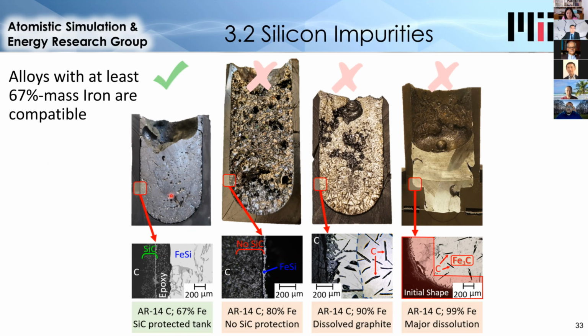So this first figure shows an iron silicon mixture that's 2/3 iron contained in a graphite infrastructure. Silicon carbide still formed at the interface, and an added benefit is that it actually shrinks slightly on freezing because iron shrinks and silicon expands, and the net effect was a slight shrinkage at this concentration. So this prevented the tank wall from breaking on freezing. So this is a pretty great mixture.